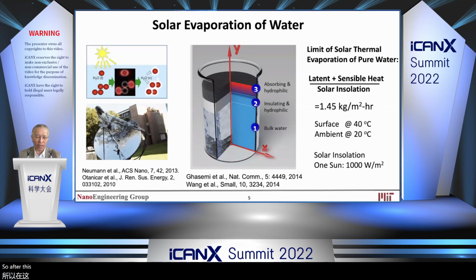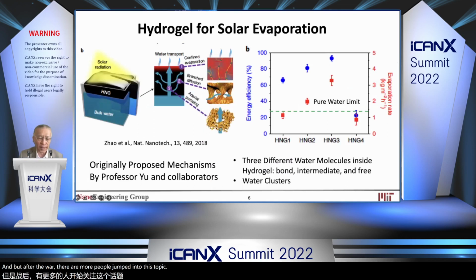After this work, and in fact we're not the only ones, there were others involved in this, and more people jumped into this topic. Surprisingly, in 2018, a group from Professor Guihua Yu at UT Austin reported using hydrogel, which is a polymer, added with a black absorber, making a porous material, and the evaporation rate actually exceeds the theoretical limit.